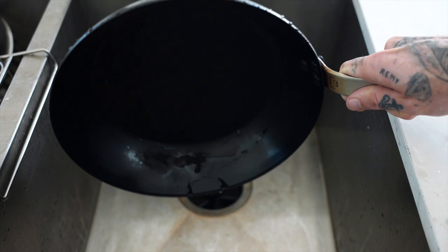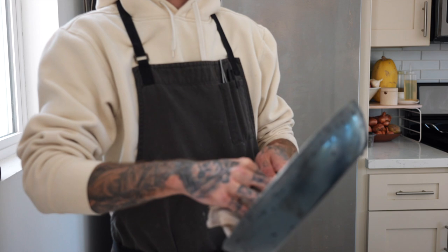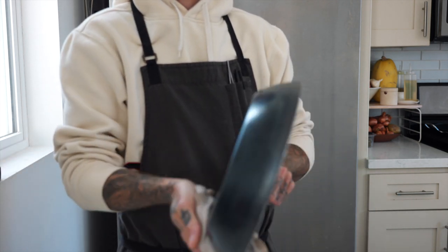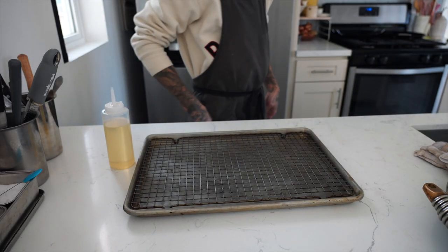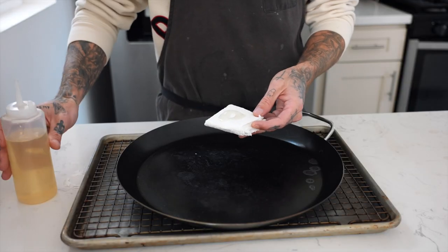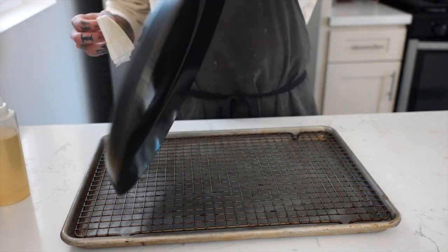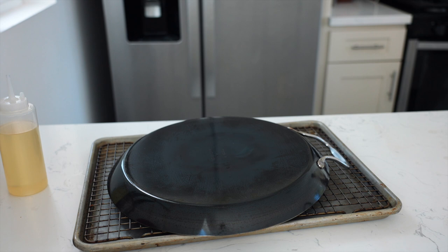Next I'm going to show you how to season your pan. First things first: I'm going to wash the brand new pan and get off any factory oils or residues, starting with a completely clean slate. I'll show you a couple of ways to season your pan. First is in the oven — this is great for really large carbon steel pans, which do come in different sizes and shapes. If your range is induction, I'd recommend seasoning your pans in the oven since it gives more even heat distribution. I have a sheet tray with a wire rack and my oil. I use sunflower oil, but a lot of people like flaxseed oil. Any high smoke point oil will do fine. I begin by wiping a heavy layer of oil on both sides of the pan, inside and out — remember, this also protects it from rust. Then I flip my towel and wipe with the dry side to remove excess so there are no drips. Put your pan face-side down, throw it in the oven at 450°F for one hour. When the time's up, turn the oven off, crack the door, and let it cool down in there.